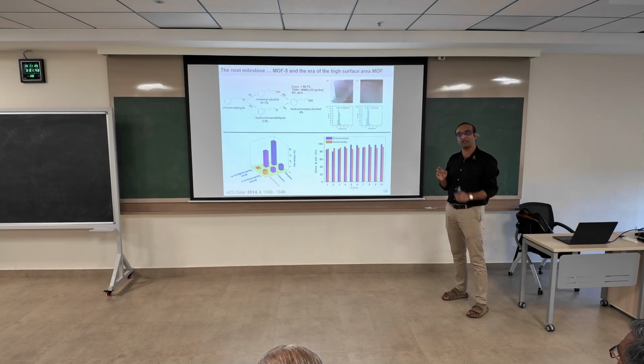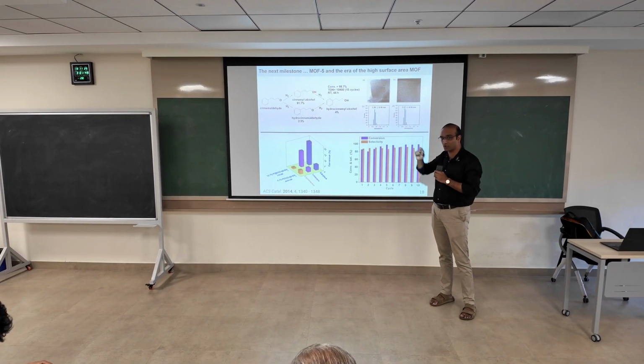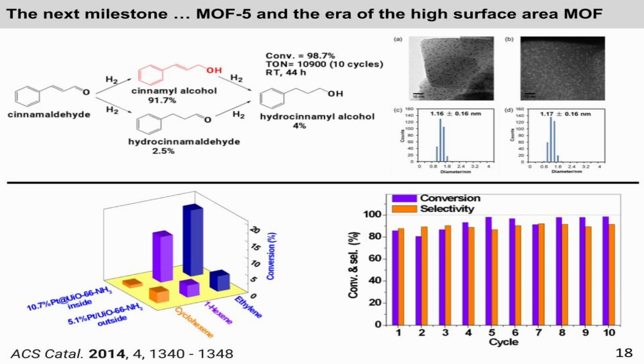This is not even a nanoparticle, it's a nanocluster. That means that with the surface area of this platinum, you're effectively using all of the precious metal that is there. Normally platinum nanoparticles will be 5 or 6 nanometers or larger when you make them by any other method. But with this method, where we loaded the precursor first inside the MOF and then controlled the size, because of the encapsulating environment that the MOF gives, you could strictly control it to about 1 nanometer.